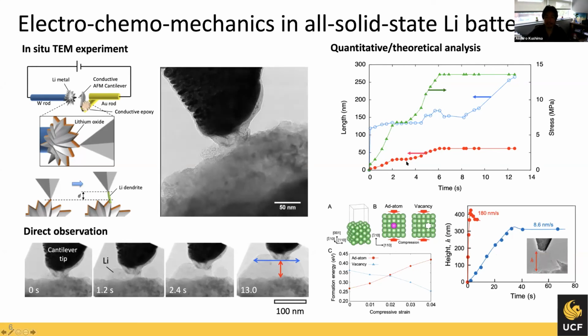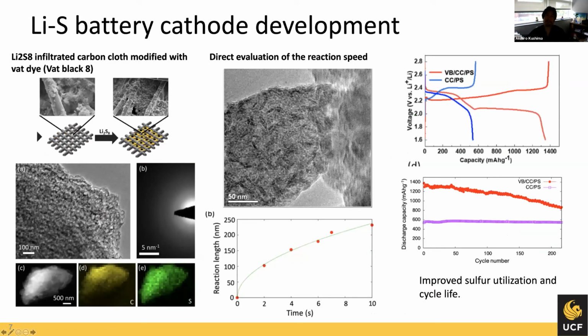And I've also been working on the cathode side. I've just introduced anode and electrolyte, now going to the cathode. For the cathode side, I've been working on lithium-sulfur batteries, trying to develop new composites to enhance the cycle lifetime and also the power densities. What we used here is this vat dye. This is a graphene-like structure with some functional groups like oxide or hydroxide groups. We use this and modify the carbon cloth.